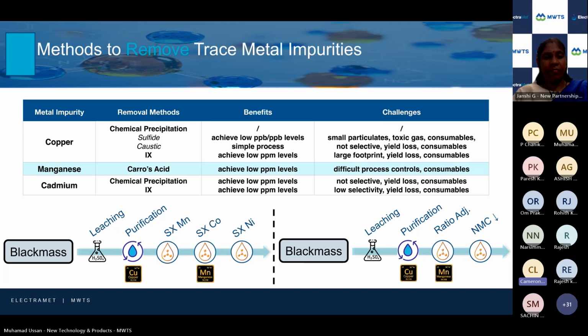Looking now at manganese, typically you add some sort of oxidizer to precipitate it out. This can work well in some streams and not in others, but also you're going to have some yield loss of that cobalt, right? You will react with the cobalt, it's not selective, and now you're losing product.